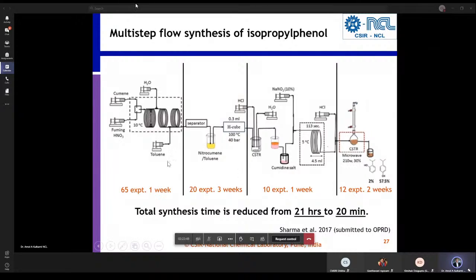So you can look at the range of conditions which we have covered from the left hand side to the right hand side, and look at the total time: the typical conventional synthesis at the lab scale needs 21 hours. We have reduced it end to end to 20 minutes. So this saves a lot of time. It also gives you a lot of flexibility: you can change the starting materials, you can change any of the intermediate substrates, you can make a library of molecules. So doing chemistry in flow saves a lot of time and also makes you more creative.